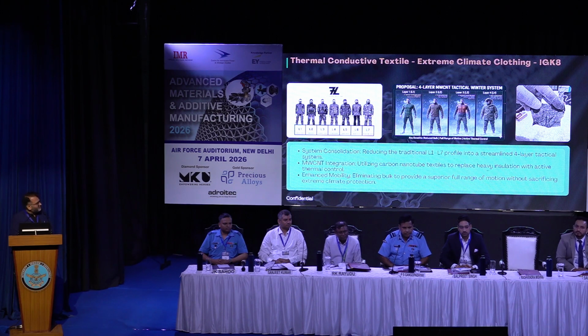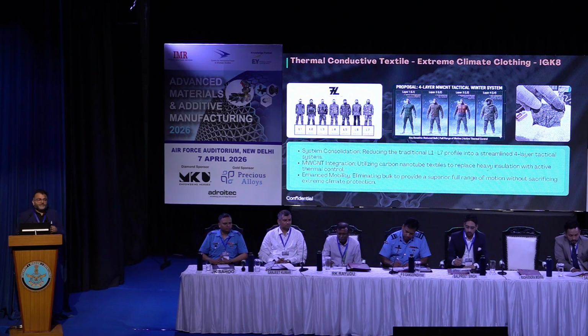Now this is one of our personal favorites. When you are at minus 50 degrees in Siachen and all, you have around 7 layers of jackets which you have to wear to survive, and it stops your mobility. It creates a problem that it makes a lot of noise when you try to move around, and then you are just depending on passive heat, the heat the body is generating, and you are trying to retain that heat. We observed that with nanoparticles, with a small amount of electricity, we can generate heat and you can eliminate a few layers of the jacket.